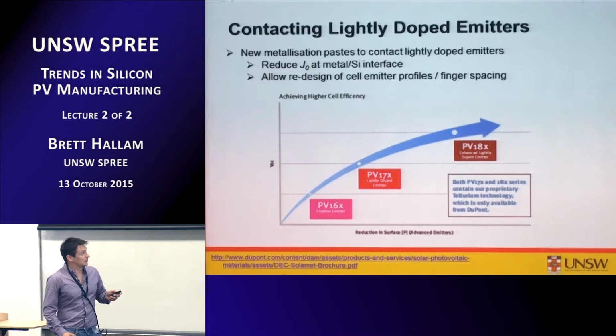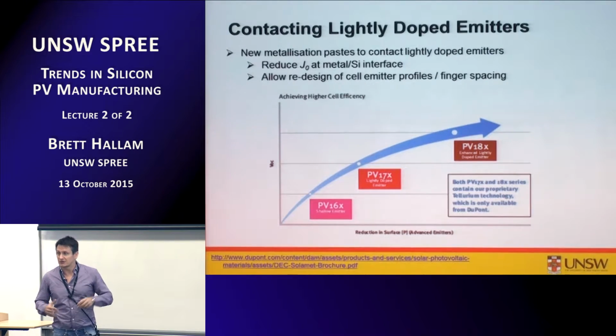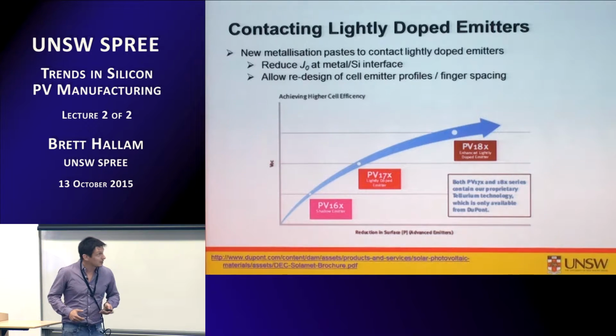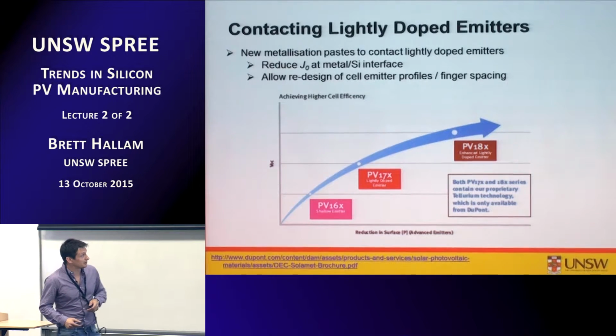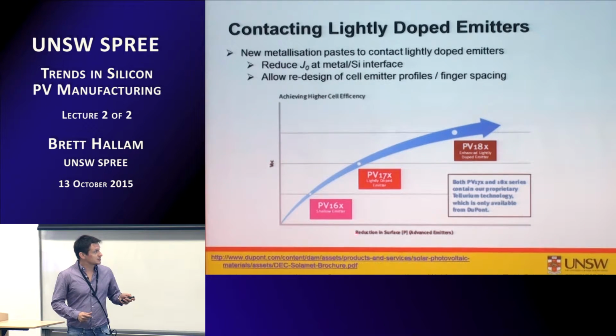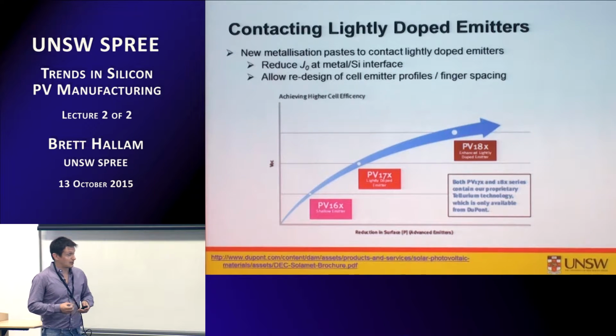In terms of going to lightly doped emitters, that also faces challenges, as I mentioned. This was probably not a perfect graph of what I was hoping to include, but basically it shows that as we reduce the surface concentration of phosphorus, you need to change how the paste is made to allow effective electrical contact to that doped surface, and reduce the J0 or maintain a relatively low J0 and not increase the series resistance or the contact resistance at the metal silicon interface too much.